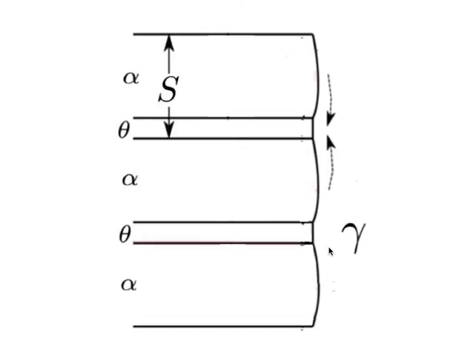Ferrite has a low solubility for carbon and cementite can absorb huge quantities of carbon — it is an iron carbide. The carbon that cannot be accommodated in the ferrite goes towards the cementite which absorbs it. The diffusion direction here is totally different from all other cases: it is parallel to the transformation front, still diffusion in the volume of austenite but parallel to the interface.